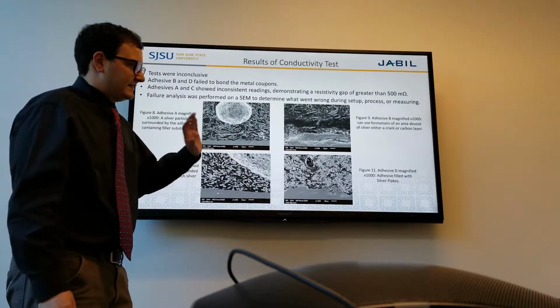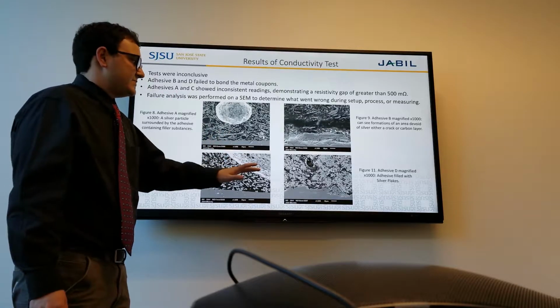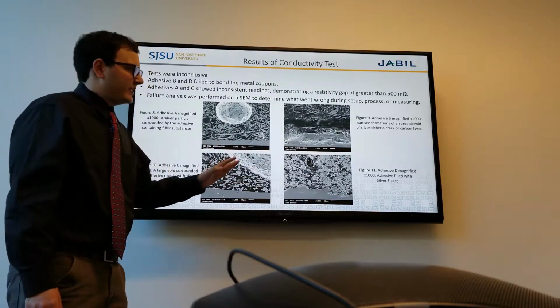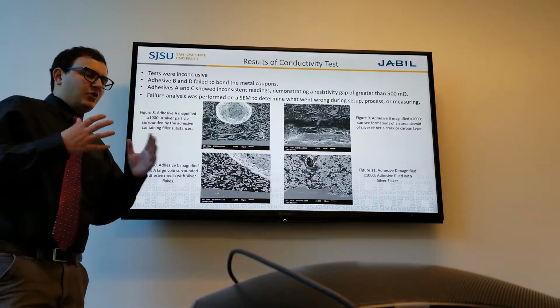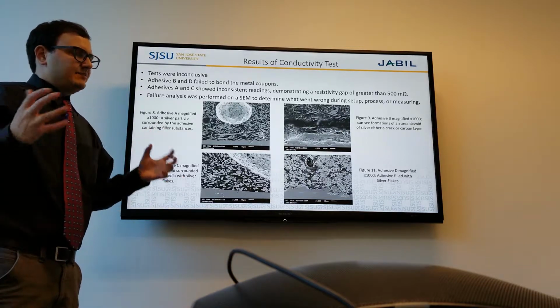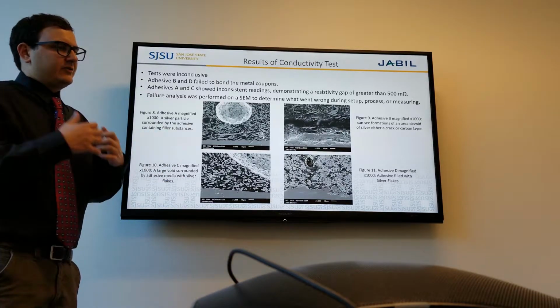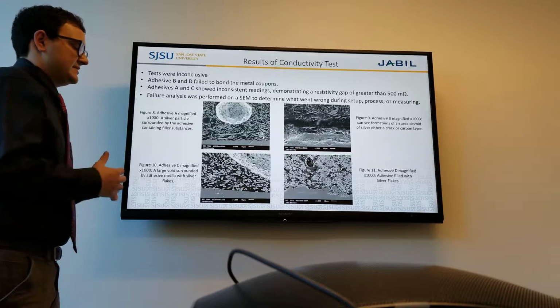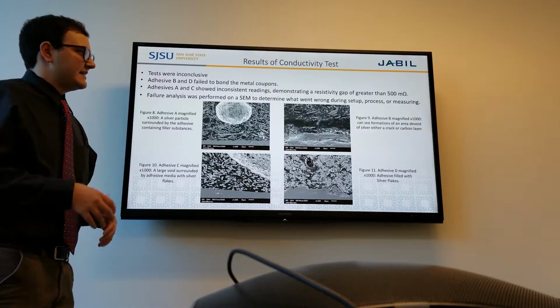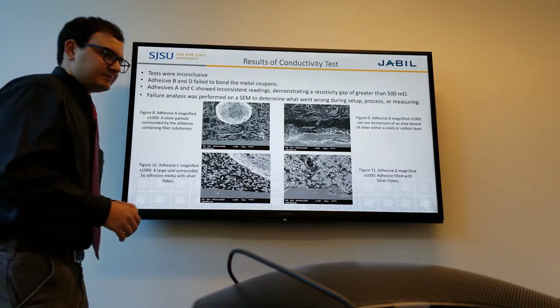Adhesive D lacked the strength. You can tell this because it's filled with silver. A general rule of thumb for conductive adhesives is that the more conductive material you have, the less bonding material you have. Therefore, the strength is less. It did not have the strength to support the weight of these stainless steel coupons, and therefore it just fell apart.